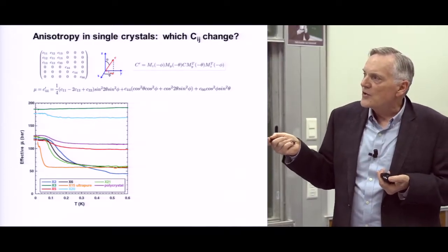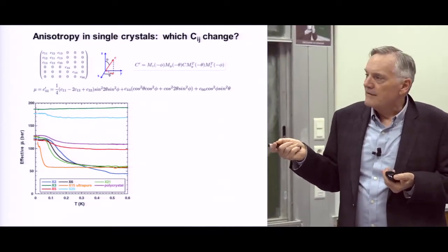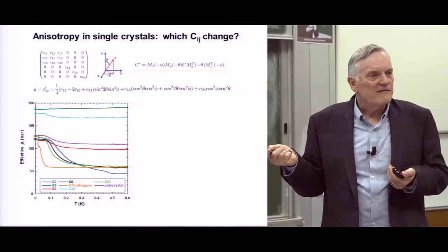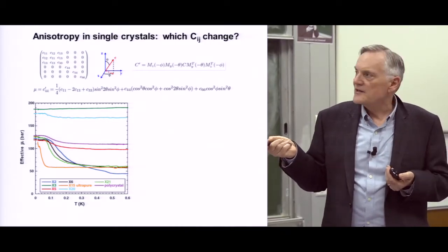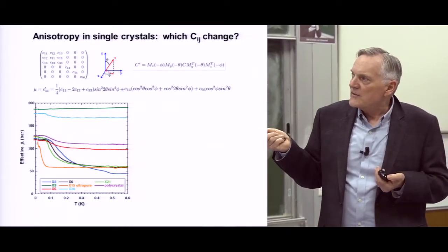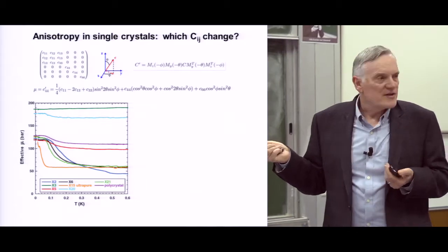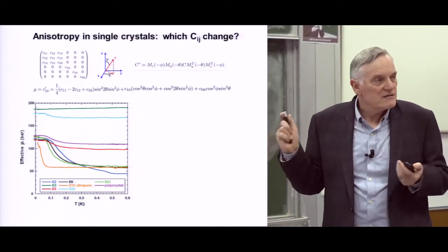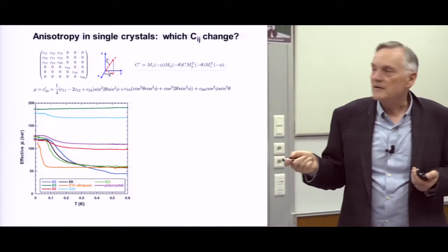These are all ones, though, you know the angles for. And actually, somebody has measured the five elastic constants, not their temperature dependence. And if you plug those in with these angles, they agree for every crystal. The zero temperature value is just the perfect crystal.